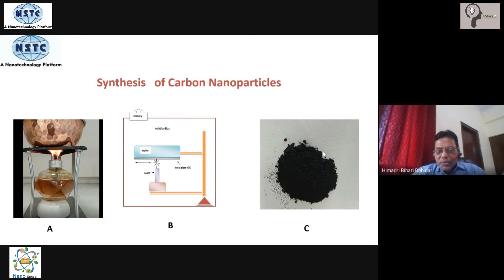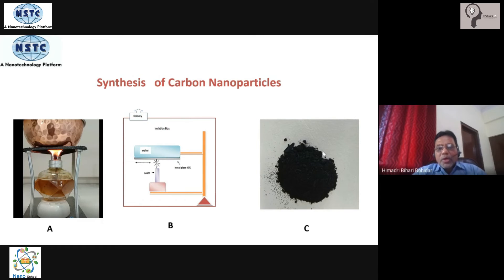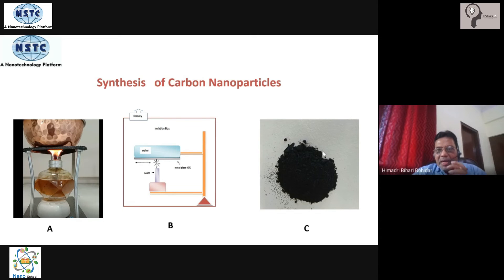There is no toxicity involved anywhere. Allow this experiment to run for two to three hours. After that, remove the flame and let the plate cool down to room temperature — this takes a couple of hours, or you may leave it overnight. Next morning, use a clean spatula and scrape the carbon material deposited on the surface of the metal. What you see in panel C is a carbon dust, a carbon powder — and these carbon particles are all carbon nanoparticles synthesized at low temperature.